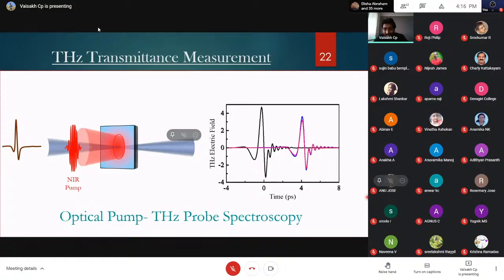on an excited sample. Excited could mean you have heated up the system, or you have generated electron-hole pairs. This can be done using another femtosecond pulse. And you can see here, the pulses I show here: one is through air, the blue is the one that has passed through indium nitride, and the red, with a slightly lower amplitude, is the one that has passed through photo-excited indium nitride.